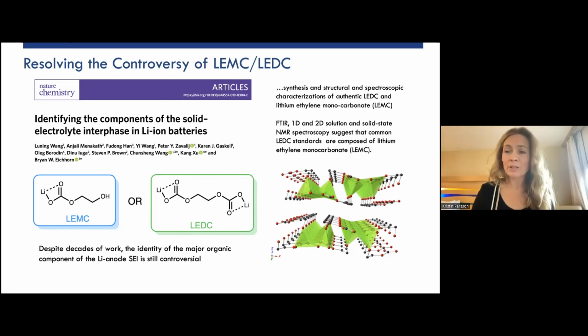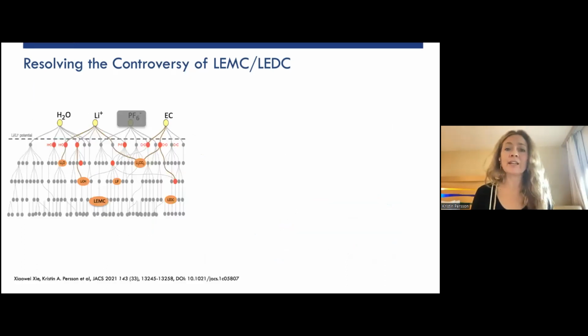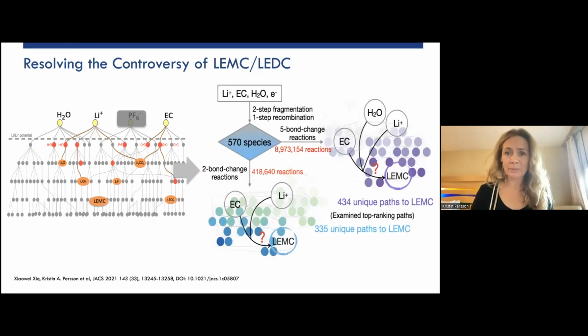So we decided to set up a new network, which in this case contained ethylene carbonate, lithium, and impurities of water, because LEMC has that hydroxyl group, so we think that water might be an important player. And again, exposing it to the electrons from lithium metal.